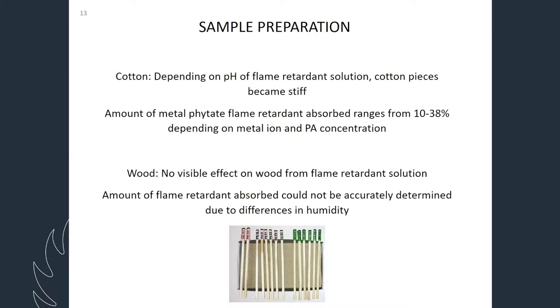One thing, this project was actually a proof of concept project. So we did not try to control humidity and other factors because it would have taken a lot of time to just prepare the samples. Rather, we tried to make the sample in a simple, straightforward way and checked, yes, they indeed have flame retardant behavior. The humidity in the room when we made the samples varied a bit, so it's difficult for wood samples to tell how much flame retardant was absorbed. But now we are working on it. I'll describe in later slides how we are controlling the humidity in the follow-up project.